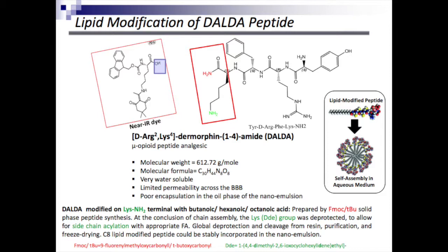The other thing we noticed is that when we modify with these lipids, these peptides self-assemble into micelles, and that micellar structure, even when present in water, has a much greater stability against proteolytic digestion compared to the free peptide, because the enzymes are no longer able to access the amino acids and the peptide chains as efficiently due to steric hindrance. So just by creating a self-assembled structure of these labile molecules, you're able to improve their stability tremendously. But we are also interested in getting these into the oil phase.